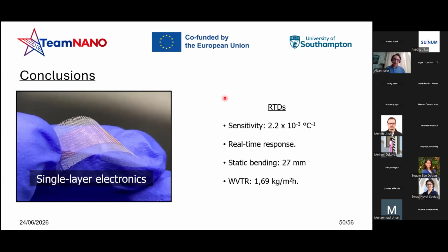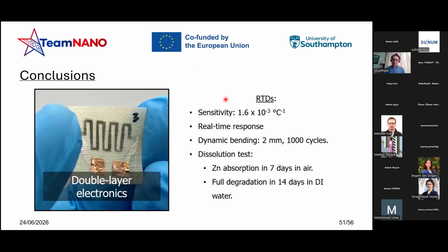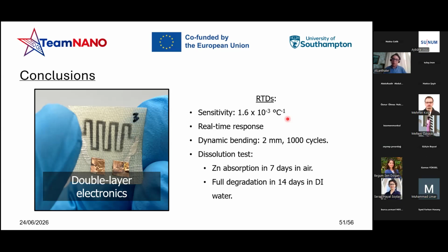So, as a conclusion of my speech today, I would like to sum up everything. For the single-layer electronics, for the RTD specifically, we were able to achieve a sensitivity comparable to the literature, a real-time response device, the capability of being bent down to a 27 millimeter radius, and breathable electronics in the end. For the double-layer electronics, the first one, the RTD1, again, sensitivity comparable to the literature, again, real-time response, with the possibility to withstand dynamic bending down to a 2 millimeter bending radius for 1,000 cycles,